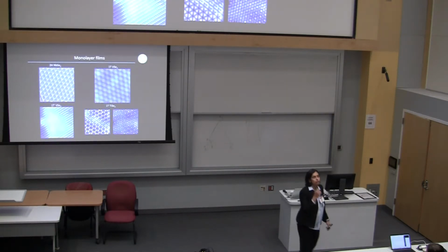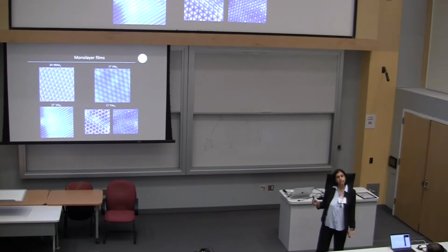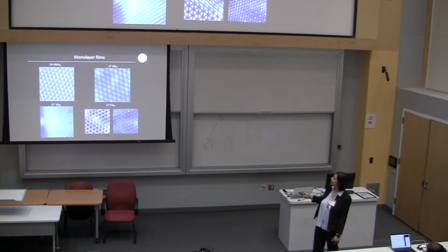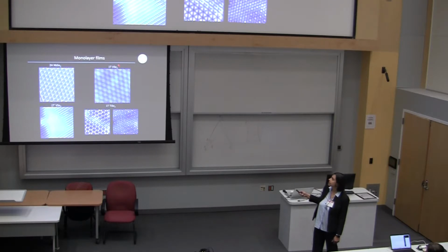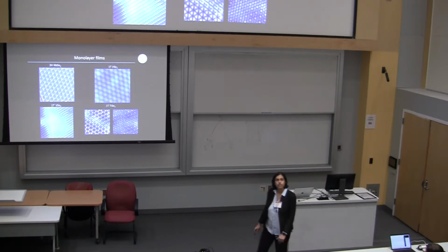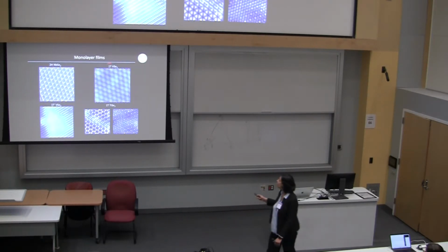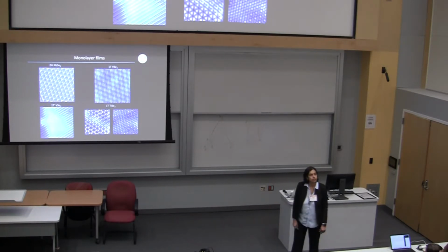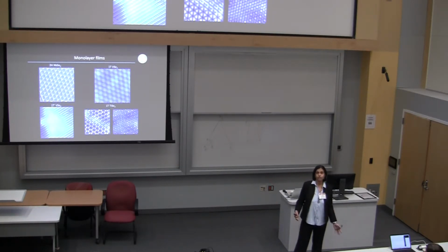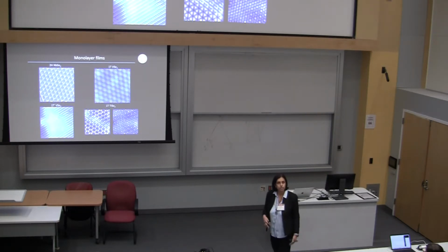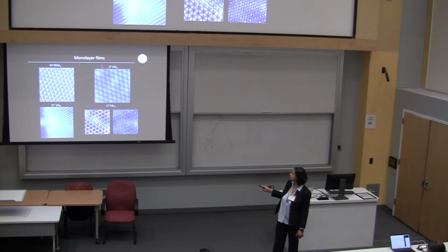These are the sort of the monolayer films we've grown recently. We've grown monolayer and bilayer niobium diselenide, vanadium diselenide, titanium diselenide, and in each of these cases, there's a particular reason. Niobium diselenide, because superconductivity in the monolayer limit is very interesting. Vanadium diselenide, because it's expected to be ferromagnetic, so we were hoping that if the ferromagnetism is strong, we might be able to use it as a substrate to grow a topological insulator and get proximity effect. So that's the reason to grow this.